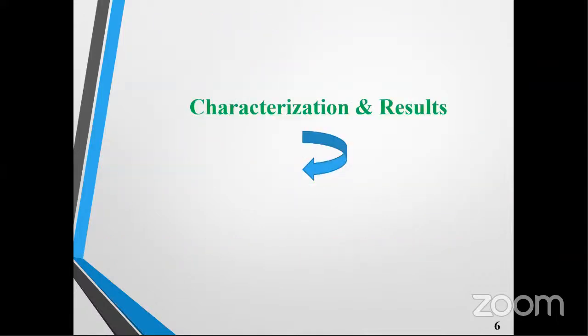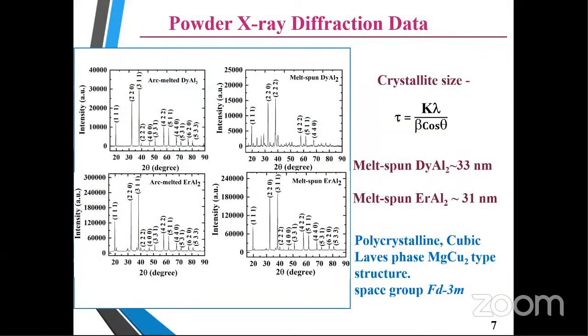Now we'll talk about characterization and results of my samples. I have chosen arc-melted DyAl2, melt-spun DyAl2, arc-melted ErAl2, and melt-spun ErAl2. From this powder X-ray diffraction data, we can see that these samples are polycrystalline, cubic Laves phase, MgCu2-type structure having space group Fd-3m. I have calculated the crystallite size using the Scherrer formula, and it is about 33 nanometer for the melt-spun DyAl2 sample, and about 31 nanometer for the melt-spun ErAl2 sample.